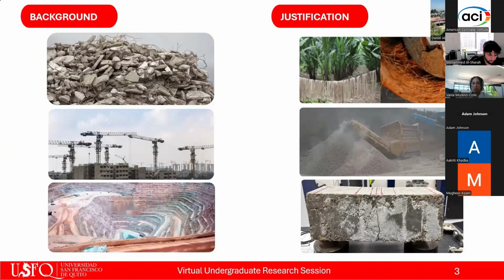Yet, recycled aggregates often have lower quality and higher impurities, raising water absorption, reducing workability, and weakening strength. Fibers, particularly polypropylene, can improve tensile resistance and limit cracking, but they are not eco-friendly. Here, natural fibers like coconut and abaca, abundant in Ecuador, emerge as a greener alternative. This study, in collaboration with Holcim SA, evaluates concrete made with recycled aggregates and natural fibers, comparing it against traditional mixes with natural aggregates and synthetic fibers, aiming to propose sustainable large-scale solutions.